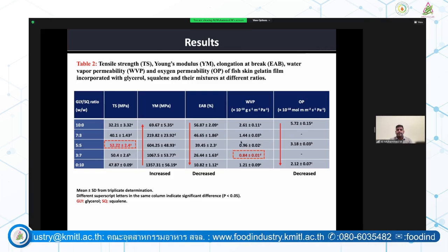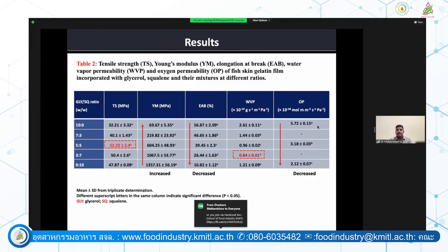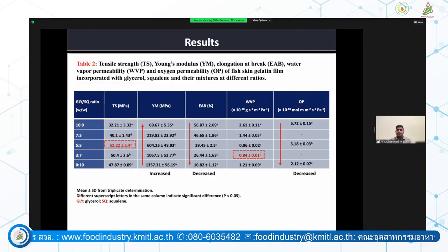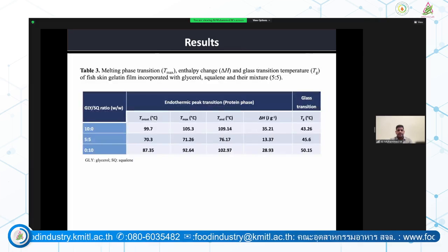And we can significantly see there was a huge reduction in water vapor permeability. So this indicated that the water vapor or moisture permeability across the film can be significantly reduced after adding squalene. And the most important property we were expecting was oxygen permeability. This oxygen permeability significantly reduced by replacing the glycerol with squalene, and the highest reduction was observed in the highest amount of squalene added.